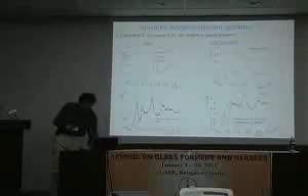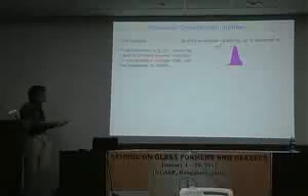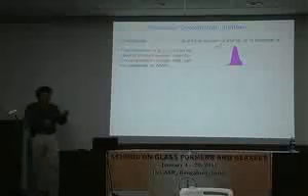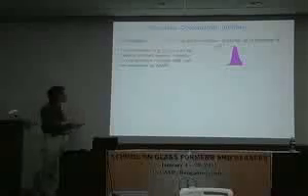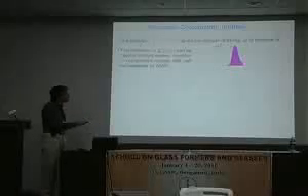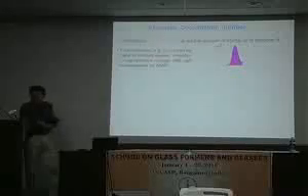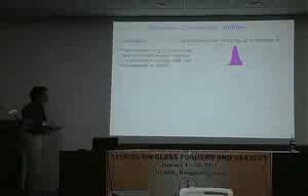Okay, so now these are the structure factors. Now let's look at a different quantity, the coordination number. If you integrate the radial distribution function from 0 up to a distance r, if you think a little bit, this gives you all the atoms that are contained in a sphere of radius r. And so if the g(r) looks more or less like this, just a cartoon, and you stop your integration at this distance here, you can estimate the number of atoms in the first nearest neighbor shell.